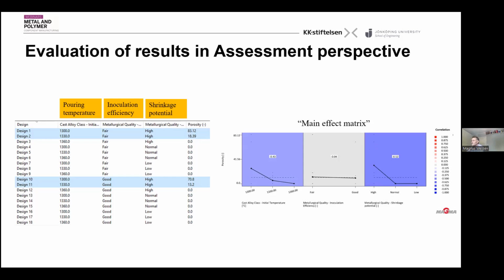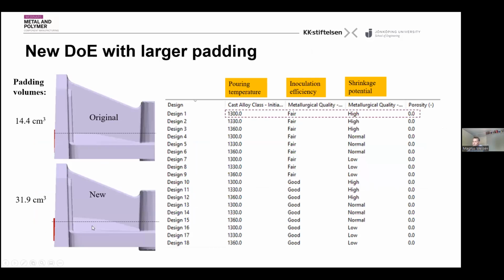So then, of course, what to do? You have to do something to make this work. This is the typical way to do things. This was the original design where I added 14.4 cubic centimeters of extra material to make directional solidification. That was quite good, but not good enough. Then I made a manual optimization in this first round of simulations: I just added a larger volume, tried it out. Then I added 32 cubic centimeters, did a new simulation, and then it worked. So that's one way to do things in a more manual way, but still using DOEs.